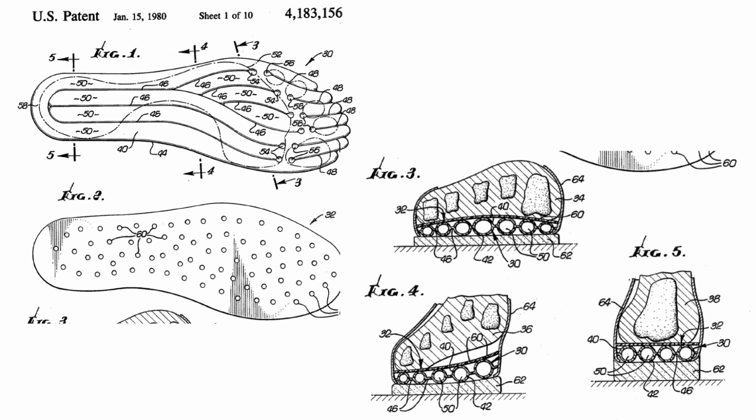Long life has been proven by 5 years of extensive testing, both in actual in-shoe tests as well as in testing machines, which simulate the duty cycle to greatly accelerated schedules. The material of the insole may be reinforced with cloth or fibers, and may be laminated with other materials to achieve better overall characteristics. The thickness of the material of the inflated insole should be between about 0.01 and about 0.050 of an inch. The fluid which fills the pressurized chambers 50 of the inflated insole should preferably be a